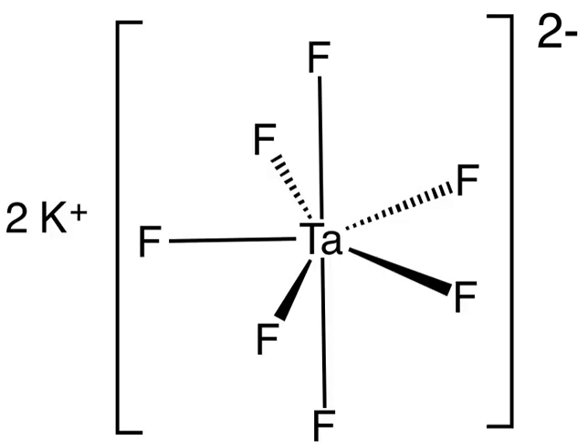The K-salt can also be precipitated from a solution in hydrofluoric acid of tantalum pentachloride: TaCl5 + 5HF + 2KF → K2TaF7 + 5HCl. Structure: Potassium-heptafluorotantalate exists in at least two polymorphs.